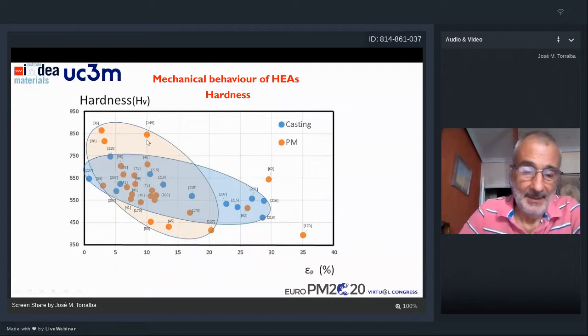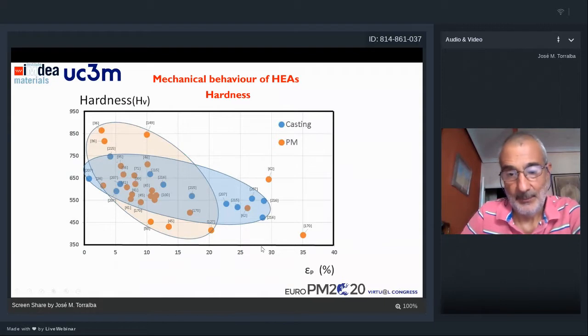As you can see, the ingot metallurgy materials can reach a little bit more level of deformation, despite we can find also some powder metallurgy materials in this area in which we can consider we have reached a high level of deformation. But most of the powder metallurgy materials are concentrated in this area, in which we have even higher levels of hardness, but lower levels of deformation.